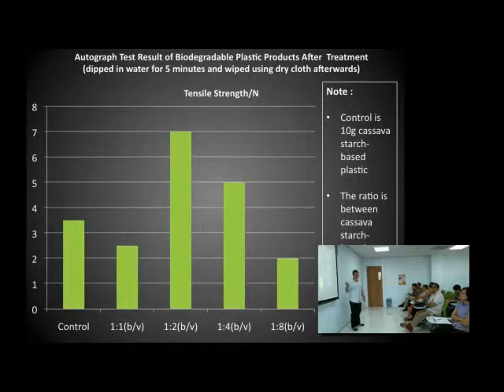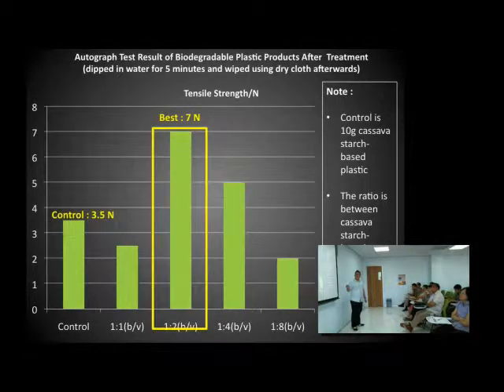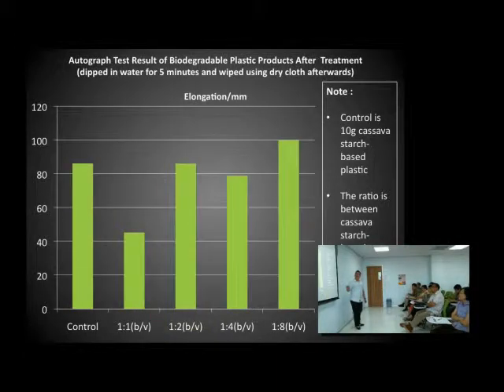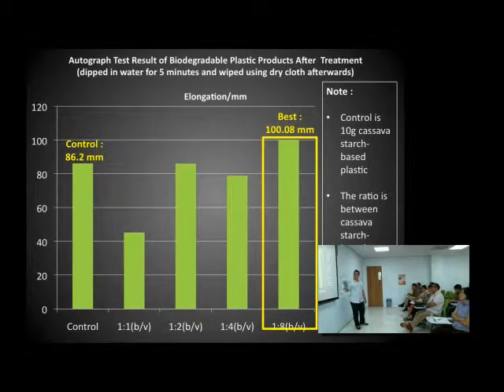And this is the autograph test result of the biodegradable plastic product after the treatment. You can see that 1:2 gives the best result. It is 7 Newton, while the control is only 3.5 Newton. And for the elongation, we have a surprising result. 1:8 gives the best result. It is 100.08 millimeters, while the control is 86.2 millimeters. But if we compare the control and the previous best, the 1:2 ratio, you can see that they don't have much difference in elasticity.